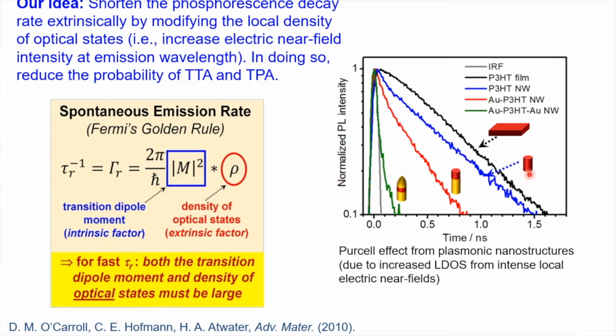For example, this is some past work I did 10 years ago, where compared to the film and the nanowire case, when you couple a polythiophene emitter to a metal rod, the photoluminescence lifetime decreases significantly, so the spontaneous emission rate increases. And even if you insert it into a nanoscale antenna, it can really shorten the lifetime, and this is due to the Purcell effect caused by the local electric field enhancement of the metal nanoparticle.